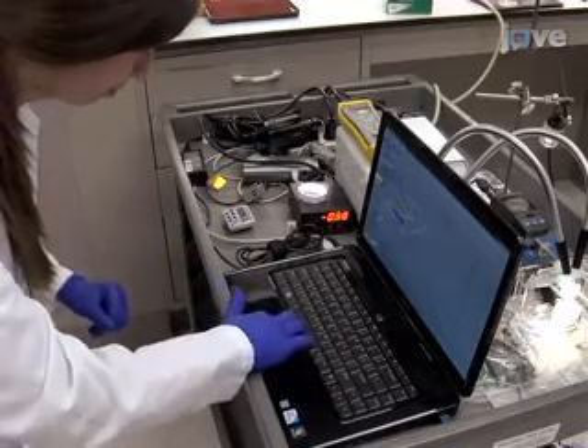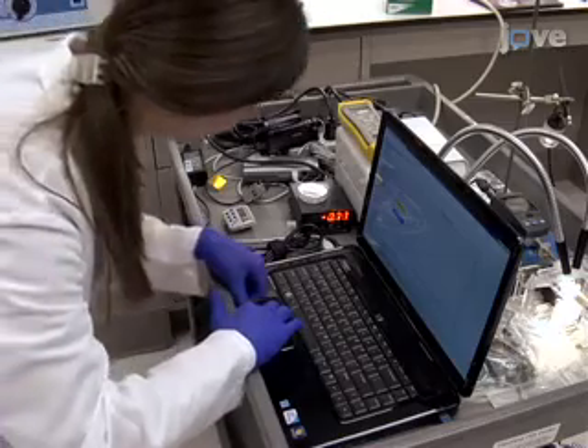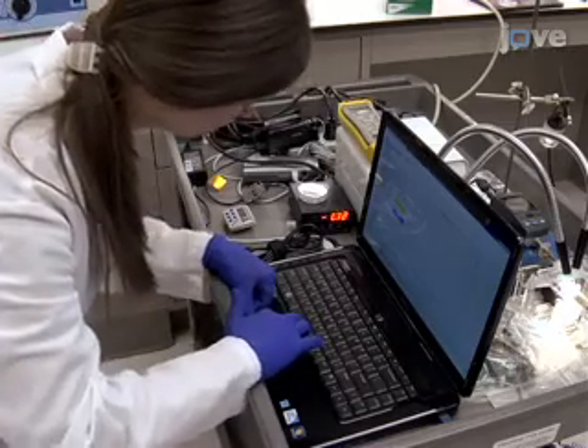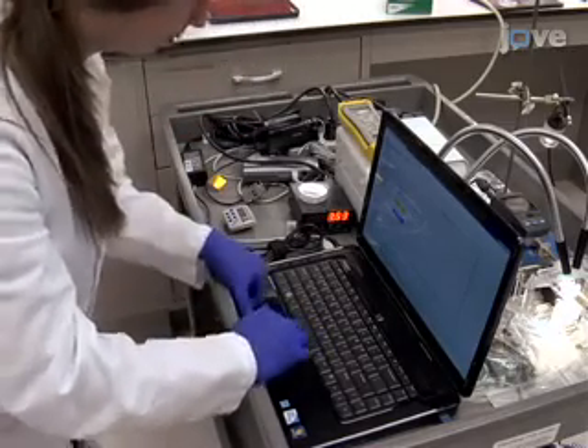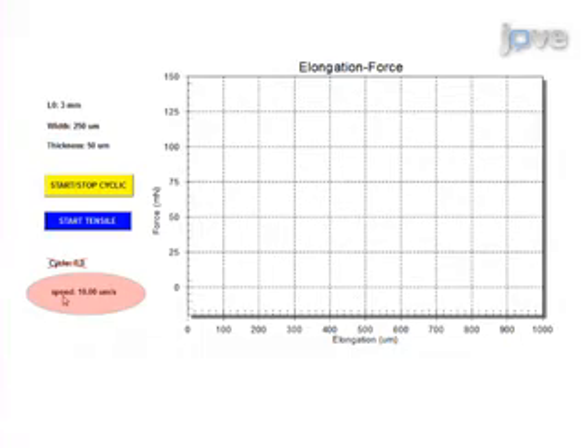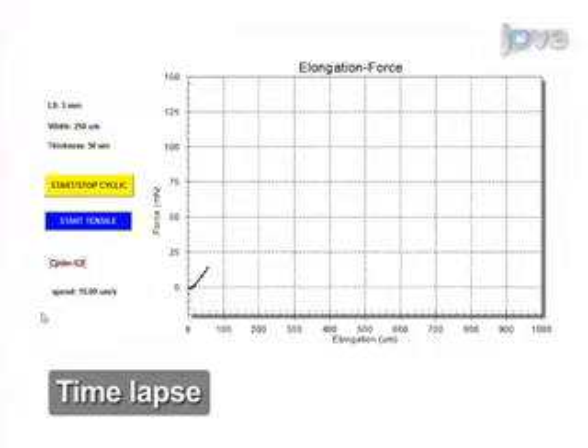Immediately after securing the sample between both clamps and within 2 minutes of explantation from the neural tissue, activate the motor in the tensile direction to elongate the sample at a constant rate. The rate here is 10 micrometers per second. Simultaneously measure and record elongation of the sample and the associated force required to strain the sample.